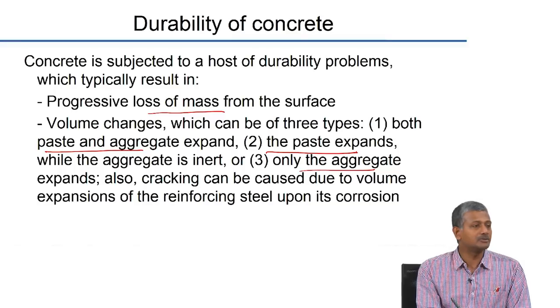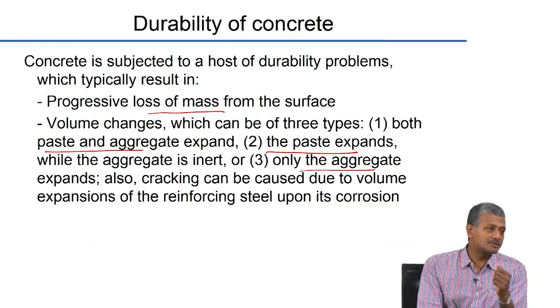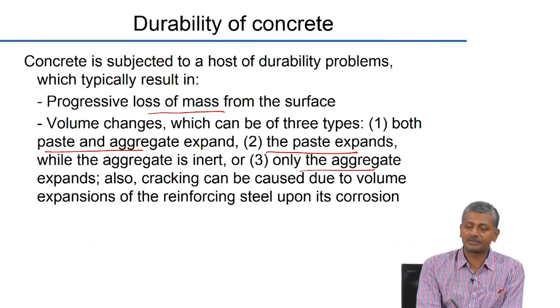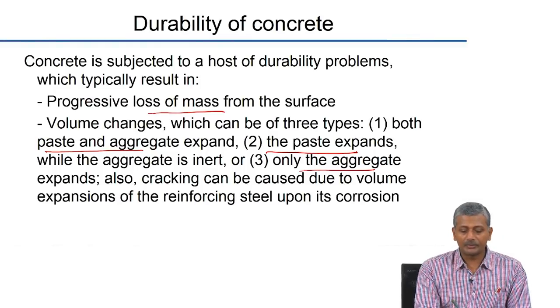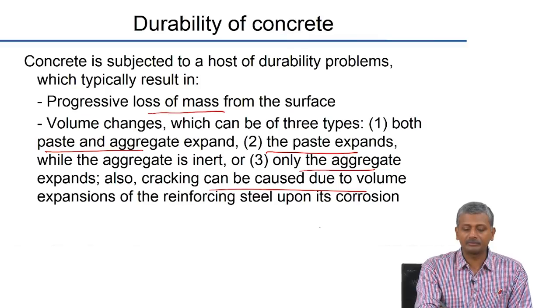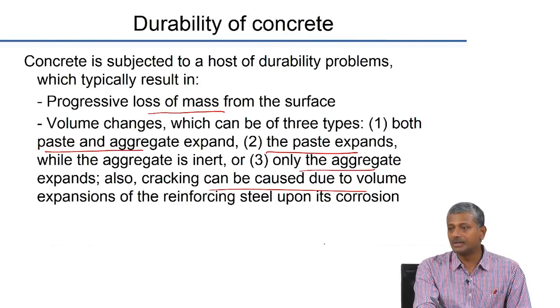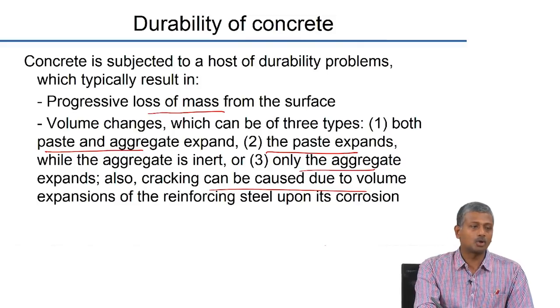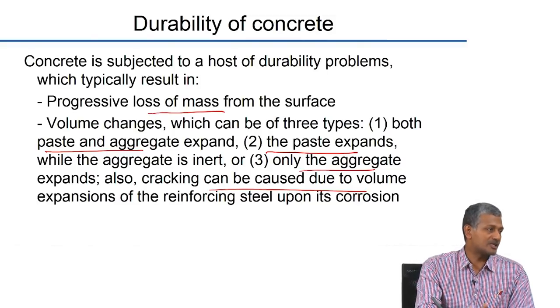The second case is only the paste expands while the aggregate is inert. When does this happen? Sulfate attack, any chemical attack basically will alter the paste, whereas the aggregate is usually inert in those processes, like sulfur attack for instance. Again, cracking due to volume change when reinforcing steel corrodes can also lead to a change in volume of the concrete, right? That can also lead to expansive pressures.